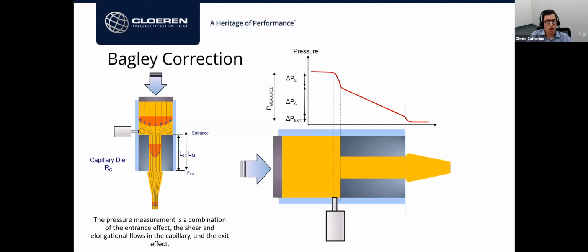The second correction is a so-called Bagley correction, and is explained by the fact that the pressure sensor is physically limited to a location upstream from the capillary die. Of course, when we want to calculate the shear stress at the wall of the die, we would need to use the pressure drop through the die.